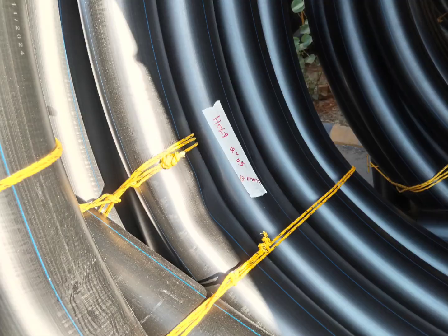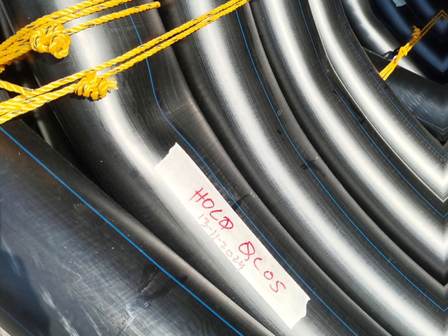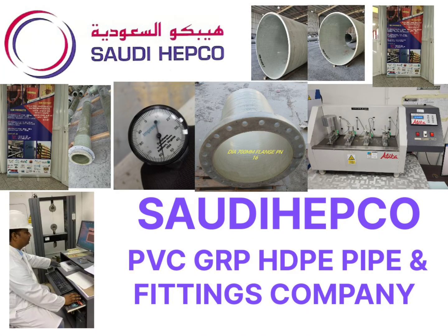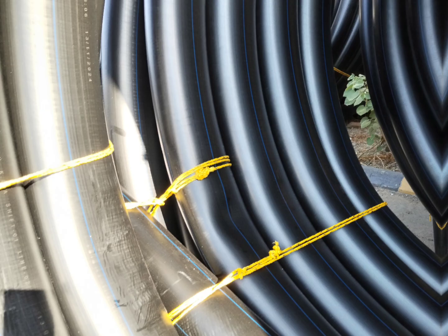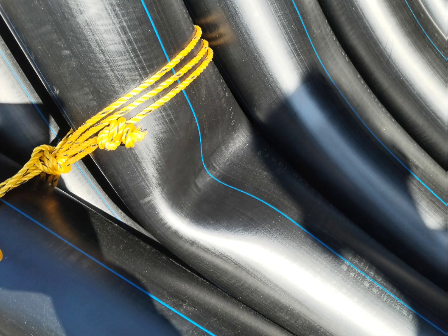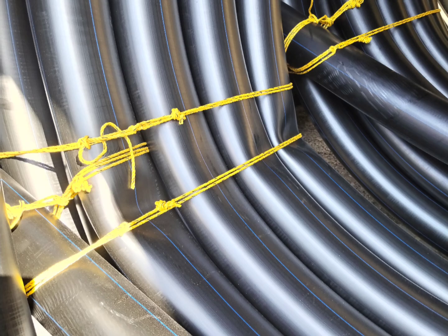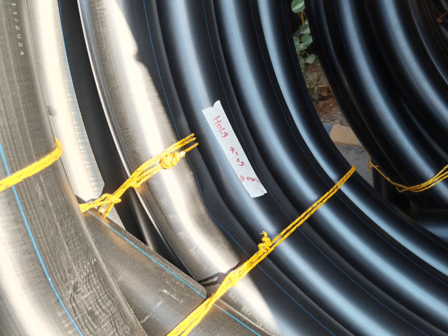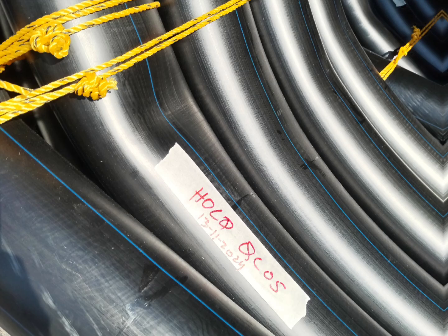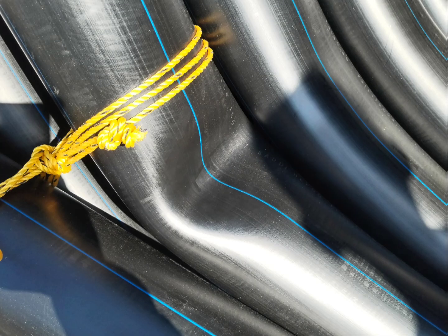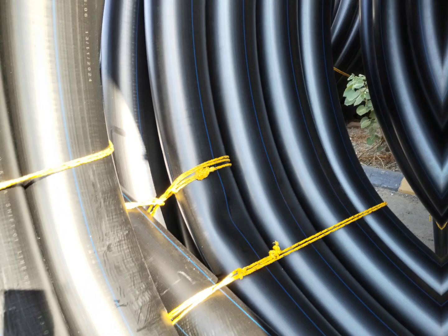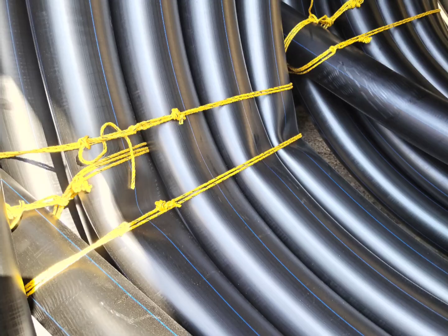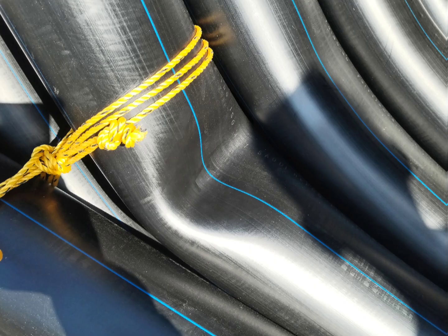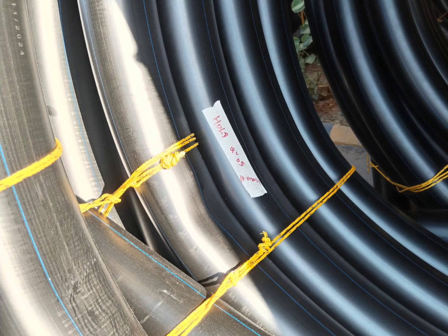1. Optimize manufacturing processes. Quality raw materials. Ensure the use of high-quality, pure HDPE resin to minimize the risk of impurities that can cause defects. Use well-regulated suppliers for consistent material quality. Proper extrusion temperature. Monitor and control extrusion temperatures closely to ensure the HDPE material flows smoothly without causing internal or external defects. Die and extruder maintenance. Regularly inspect and maintain the extrusion die and equipment to avoid any imperfections that could lead to round defects. Replace worn-out or damaged parts immediately.